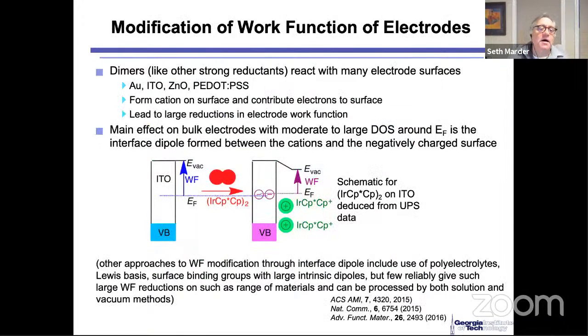Now I'm going to talk about modification of the work function of materials. So these dimers, and it's not unique to these dimers, other things will do it, can basically dump electrons into the conduction band of an electrode surface. Now, when they do that, what has to happen is that the electrons go into the conduction band. These are good semiconductors. It's ITO. So the electrons will delocalize into the conduction band. But the negative charges within the material need to be compensated by positive charges on the surface, which are the positive charges left on the ions of the dopant.